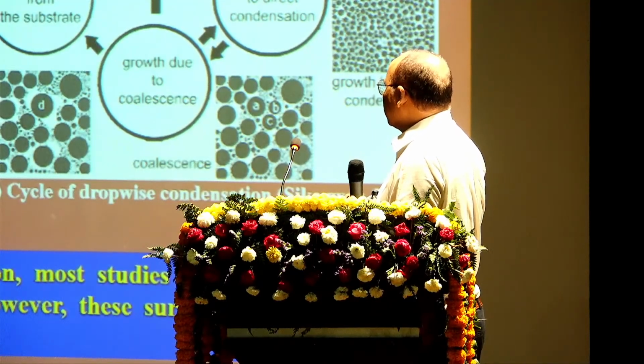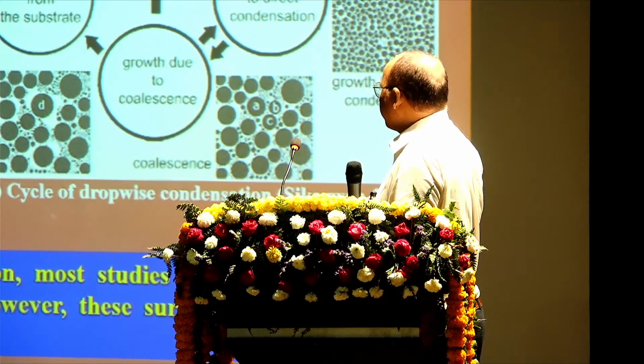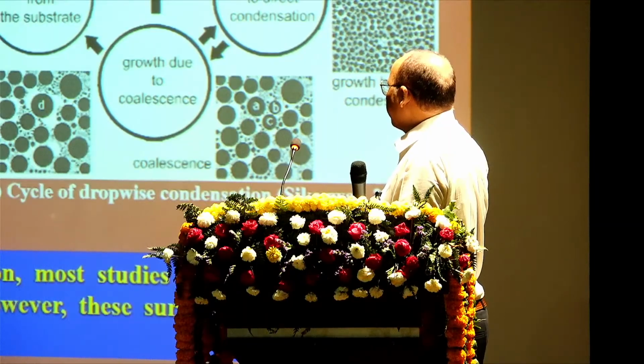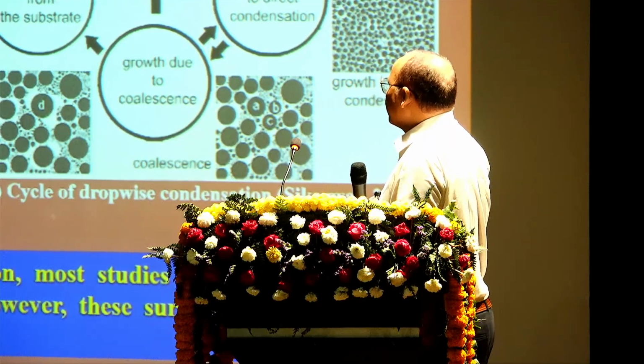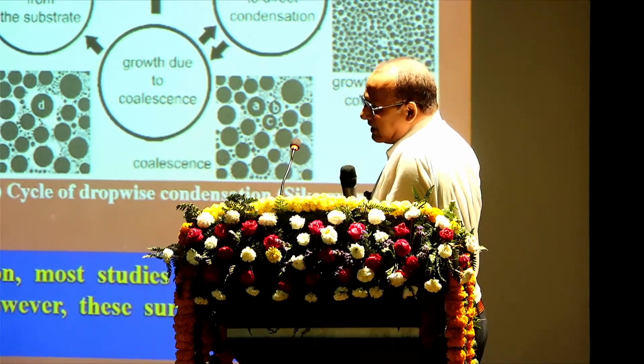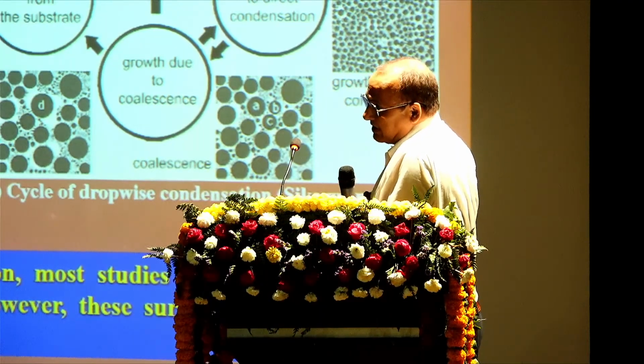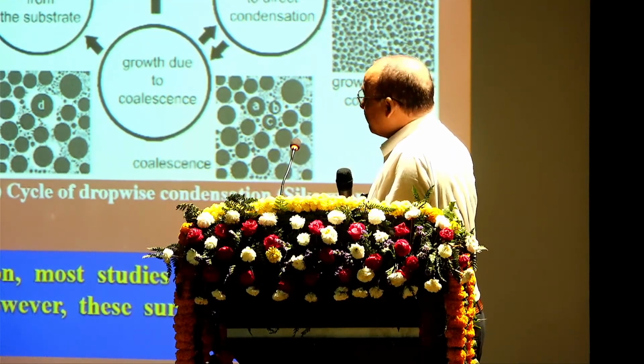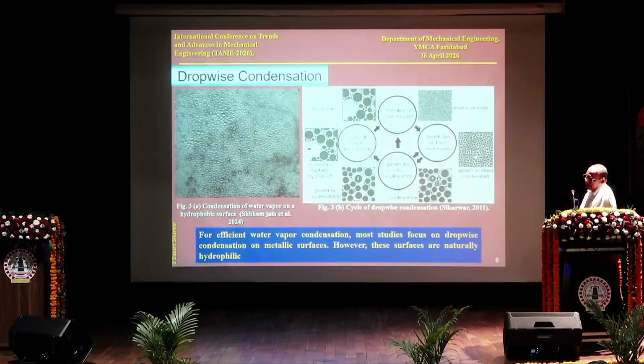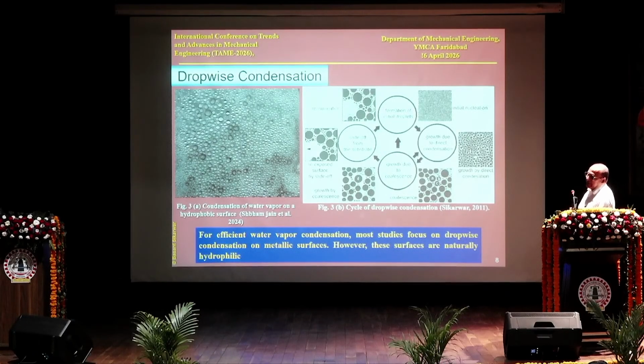Click on this video. So you see that this is the condensation on a hydrophobic surface. Water forms droplets at special nucleation sites. They grow by direct condensation and coalescence. Then they slide off or fall off, depending on the gravity direction.